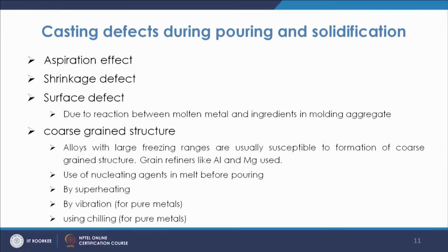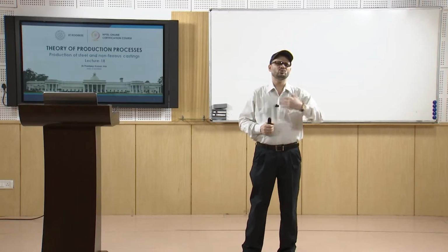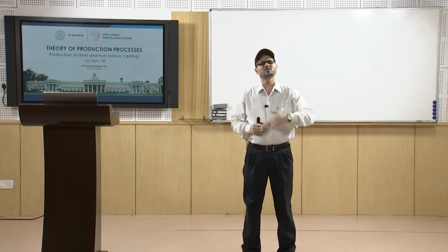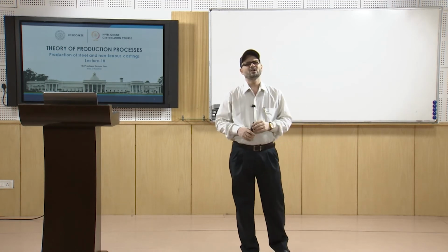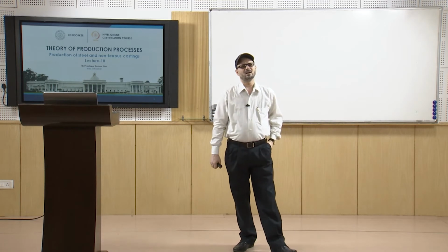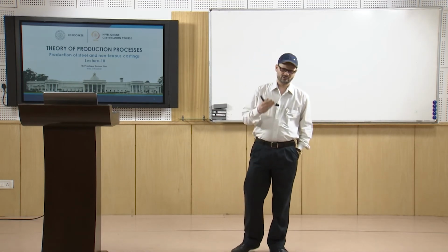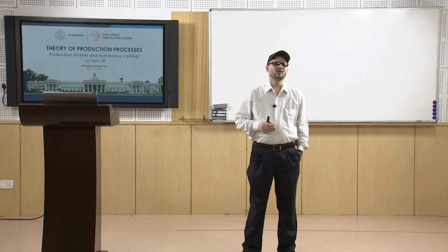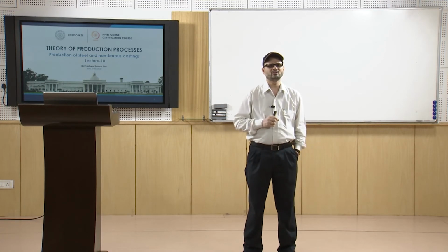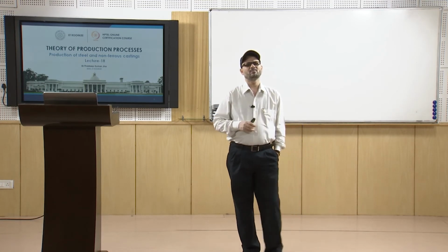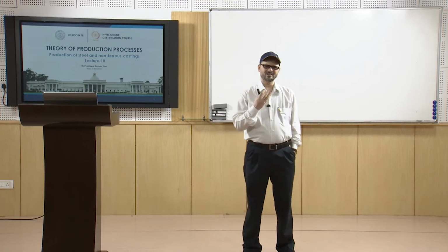Like if there is improper gating practice, you may have the aspiration effect. So, there will be sucking of atmospheric gases from the outside through the sprue or in the runner. So, that may lead to the formation of oxides, or that may lead to wastage of the material. You may have shrinkage defect because of improper size or position of the riser ring. You may have surface defect because of the reaction between molten metal and the ingredients of molding sand.